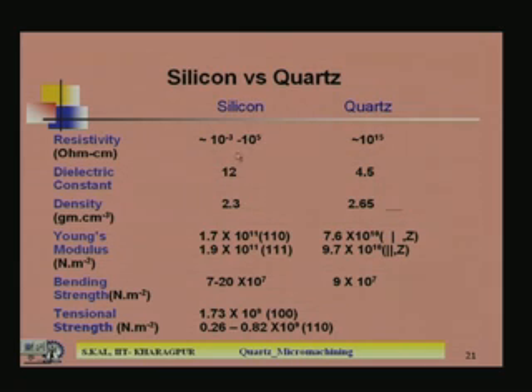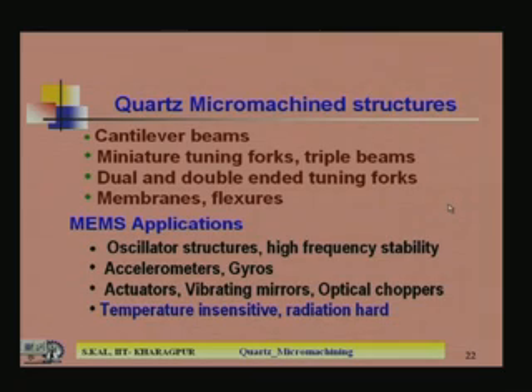Silicon resistivity is in that range, and quartz is 10 to the power 15, that means it is a much more insulating, strong insulating material. Dielectric constant is 12 for silicon, here 4.5, density is almost equal, and Young's modulus, bending strength and tensile strength are compared in this table. These are the comparison of the mechanical properties of silicon and quartz.